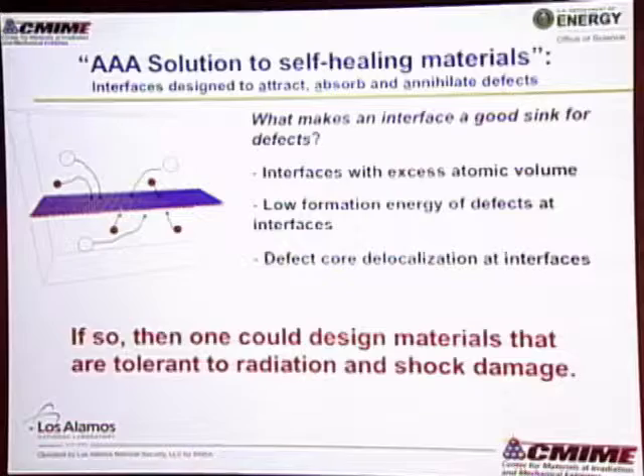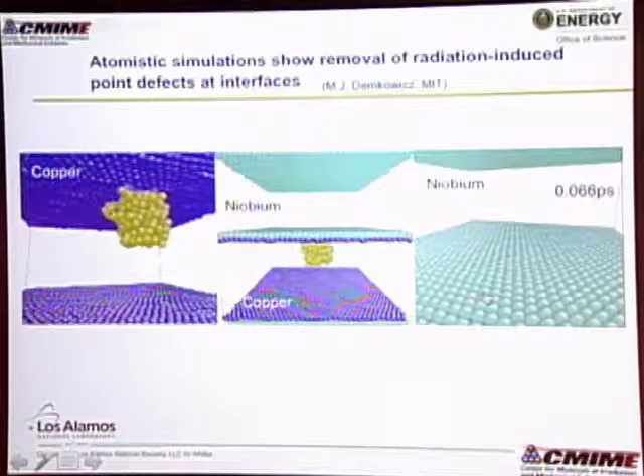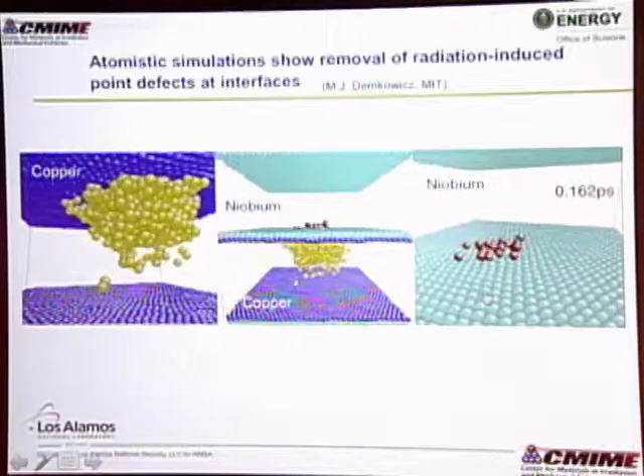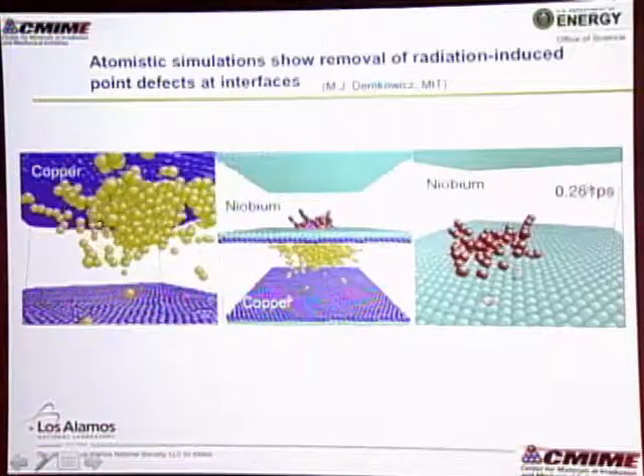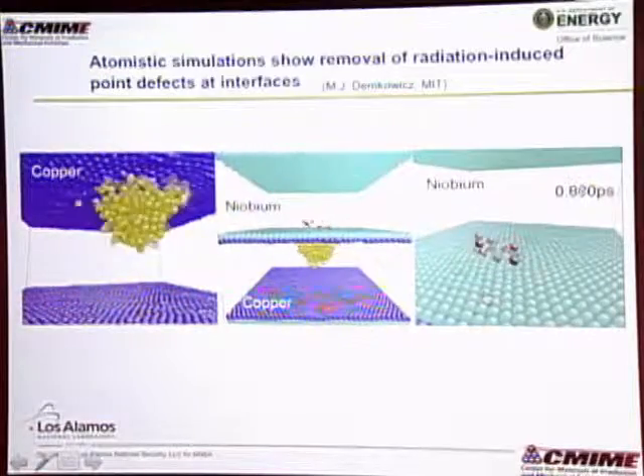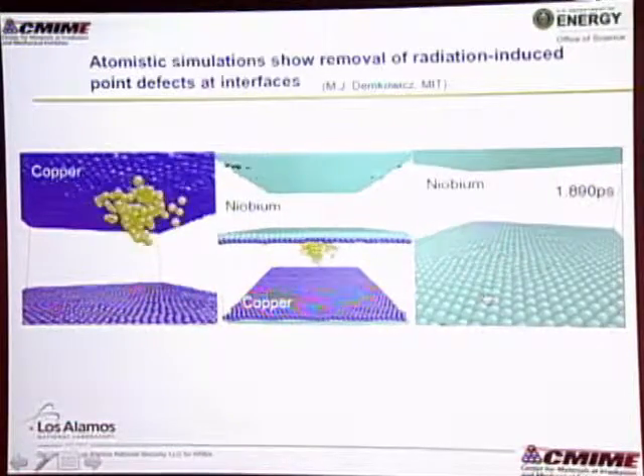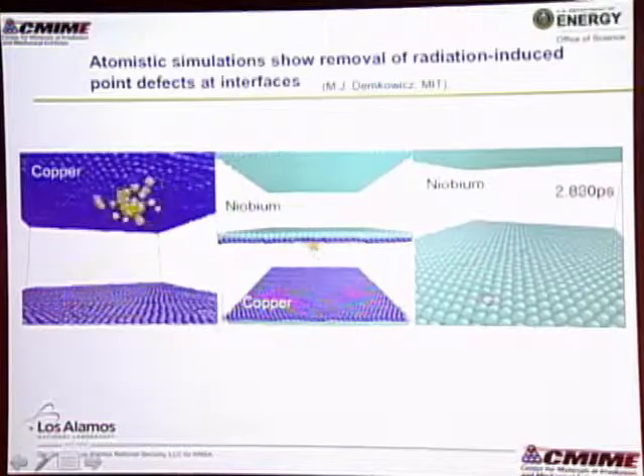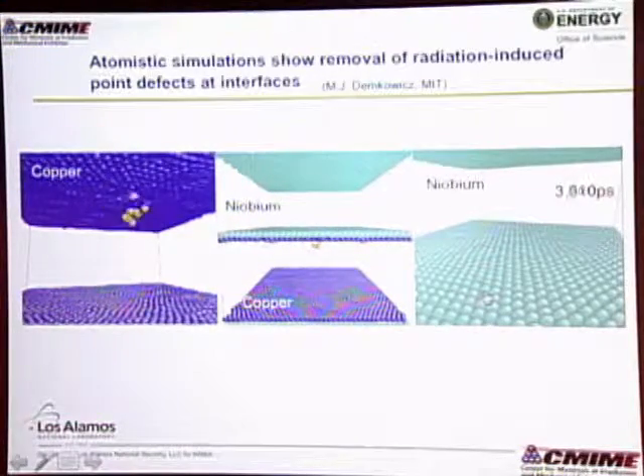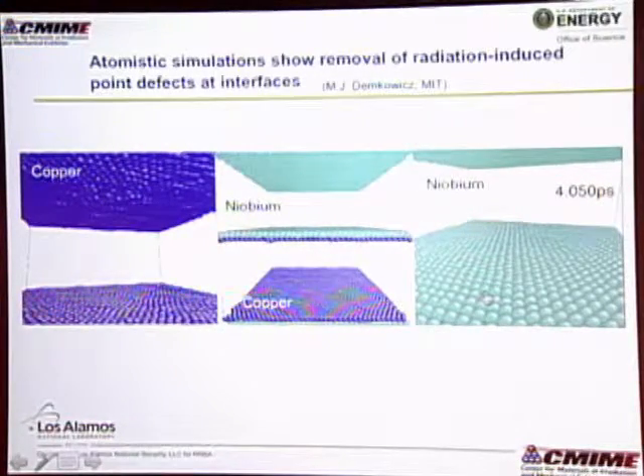If you can do this, then you can make radiation and shock damage tolerant materials. So this is what that cascade looks like if we initiate a cascade in a copper layer. So this is copper and niobium. The top here in this case is niobium, the bottom is copper, and we've removed all the atoms except for the ones here at the interface.